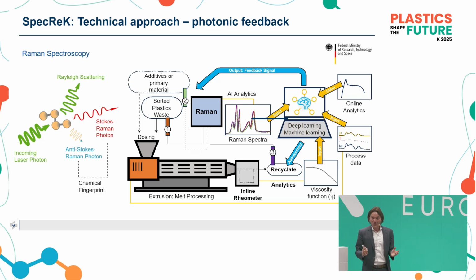So here is a schematic overview of what we are doing. On the left side, you see a schematic picture of how Raman is working, but that's not for today. On the right side, you see that we are measuring Raman both at the beginning, before entering the extrusion, online, and after the extrusion. So we can measure what happens during these individual steps. We are also measuring inline viscosity in order to see how to correlate it, and we are doing a lot of offline analytics to get that combined picture. And that will be used in order to not only control the process, but to autonomously run the process in the end. So you just feed in your recycled material, you know what the composition is, you know your target, and the process is steering itself. Okay?